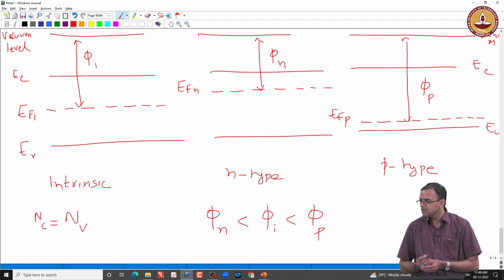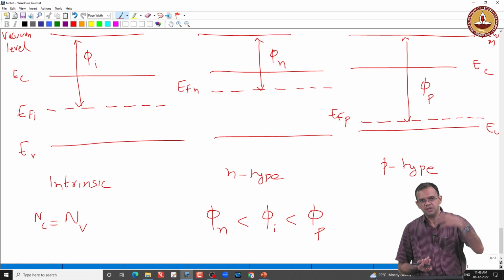So then what about doing XPS and polishing? XPS polishing, will it work? You can also do depth profiling with XPS, you are correct. But again, your dopant concentration is parts per million. At that low concentration, you may not be able to detect the signal. So that's the problem with XPS. That's why people use SIMS, because SIMS is basically secondary ion, right? So you use argon ions which then bombard out, and that has a much better resolution.